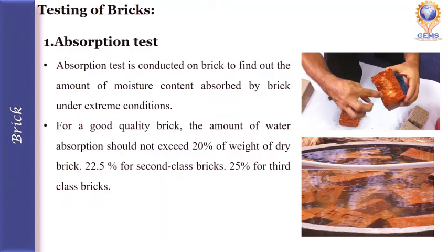For good quality bricks, the amount of water absorption should not exceed 20% of weight, and if it is a second class brick, it should not exceed about 22.5%. For a third class brick, it should not exceed 25% of its weight.